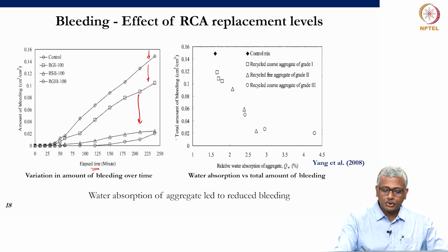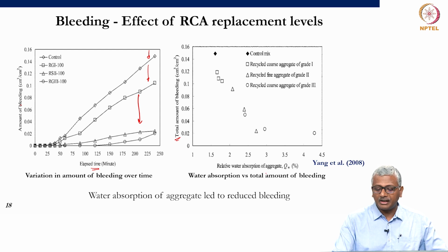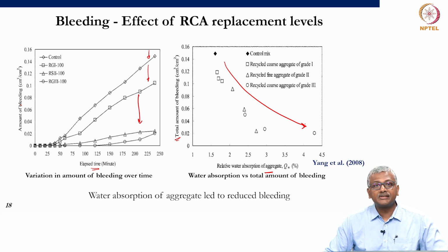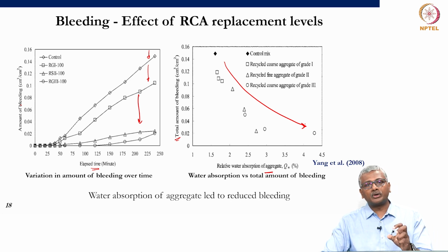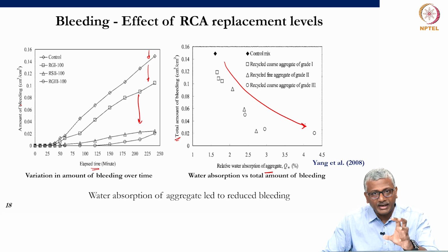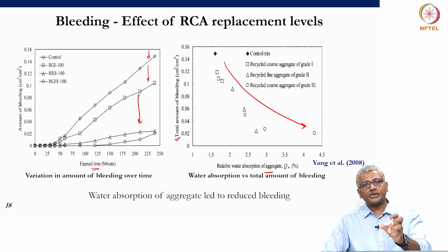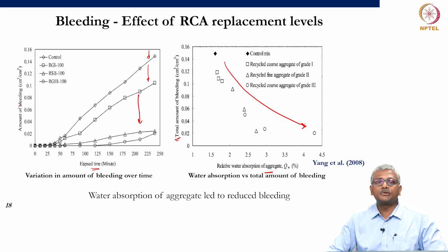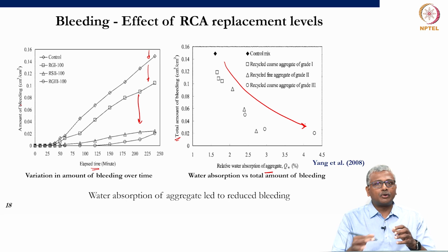Again, this is also showing the total amount of bleeding with respect to the relative water absorption in the aggregate. As the water absorption in the aggregate increases, the relative amount of bleeding gets reduced. This again says that the porosity caused by the adhered mortar in the recycled concrete aggregate leads to higher water absorption, and this water is also absorbing the bleed water, thus preventing additional water from rising to the surface. Okay. Now, this can have positive and negative connotations.